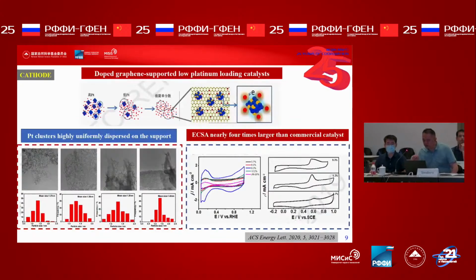It is well known that simply reducing the platinum loading in fuel cells will produce mass transfer resistance. It is interesting that we developed a new low platinum loading catalyst with largely increased platinum dispersion, resulting in decreased mass transfer resistance. However, the electronic effect generated by the interactions between them can improve the activity of the catalyst.